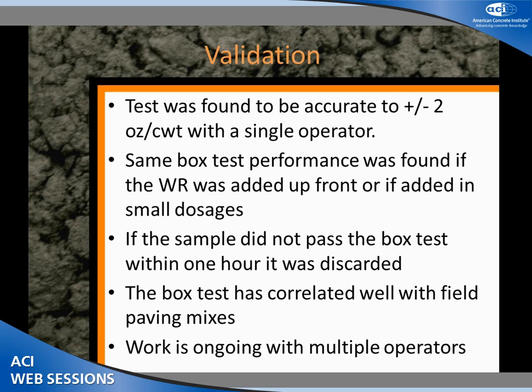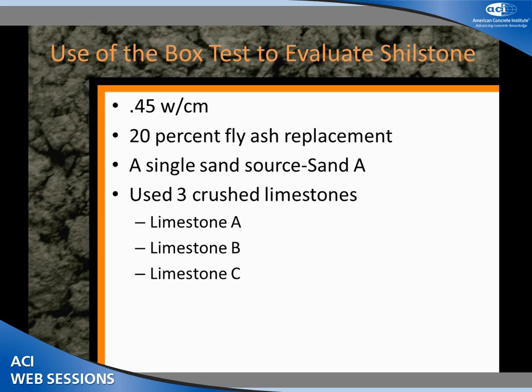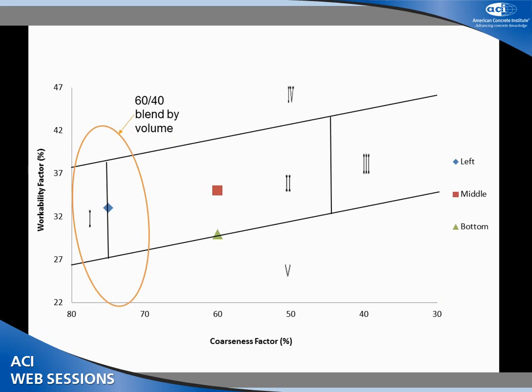So why did we do this? Because there's no test that can evaluate the workability of low slump concrete mixtures. Once we have this, we can truly start to look at gradations and what's important about different gradations. We're going to look at the 0.45 water-to-cement ratio, 20% fly ash — all five-sack mixes, single sand source, three different limestone aggregates.